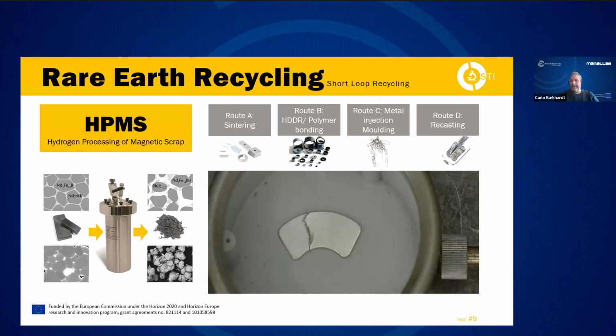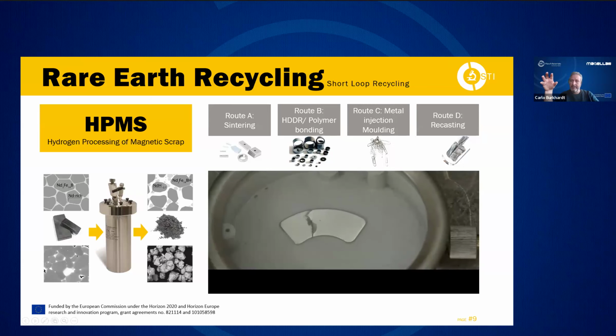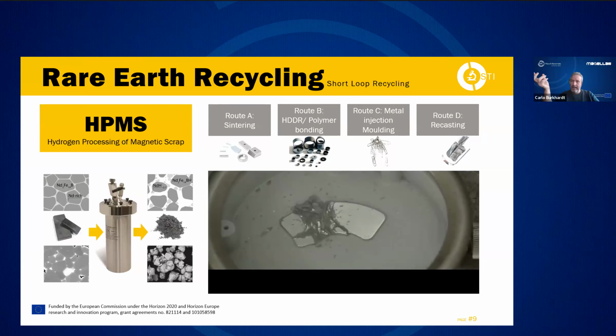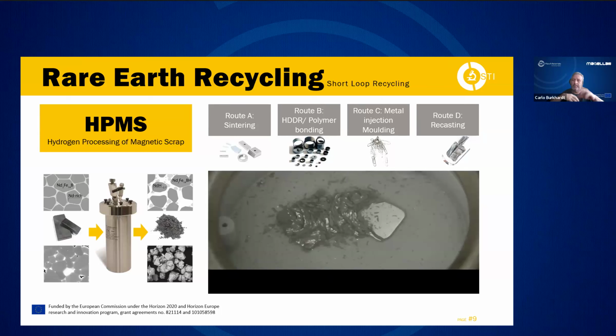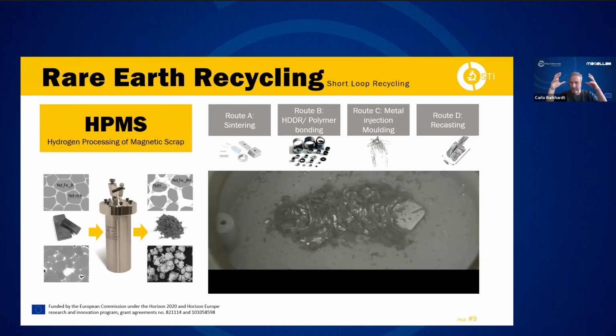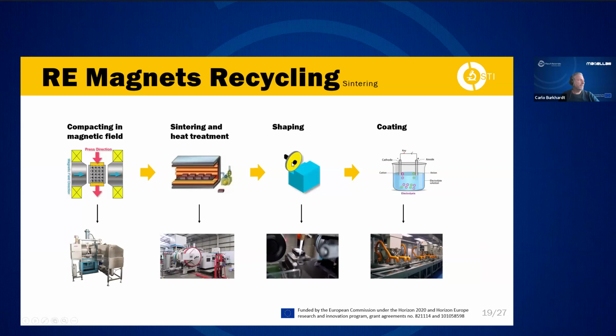But the beauty of it is that not only does this work for magnets, but it works for deeply embedded components. So you can put the corner that we chopped off from the hard disk drive into the reactor, you tumble it, and during the hydrogenation, which you see here in this video, the material is not only forming a powder, it's also demagnetizing. And so by tumbling even complete rotors or corners of hard disk drives or parts of the loudspeakers, you can separate the magnetic material, and that makes it a very cheap liberation mechanism. And that's why we think that this has a very high potential. Again, this is IP protected, in this case by the University of Birmingham.